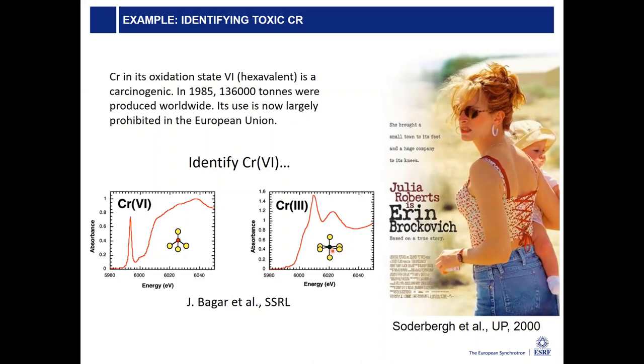And the inversion symmetry prohibits mixing of orbitals. In this case, it prohibits mixing of p and d orbitals. In this case, mixing of p and d orbitals is allowed. And the mixing of the p and d orbitals makes this pre-edge peak here so strong. So in this case, the K edge probes the local geometry, and from the local geometry, we can deduce whether it's chromium 6 or chromium 3. Yeah, so this is a nice example I actually stole from the webpage of John Bargar at SSRL.